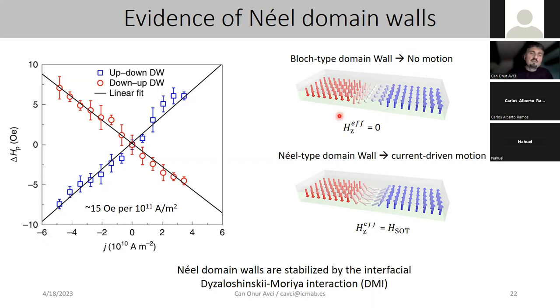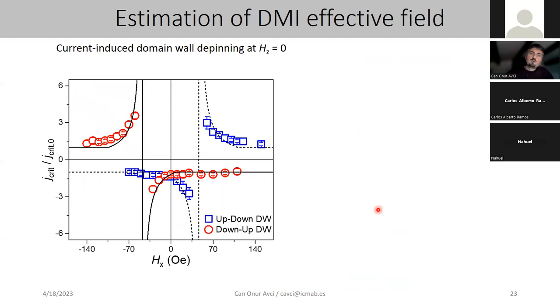We know that the spin-orbit torque or the damping-like torque cannot act on a Bloch type domain wall, which means that the domain wall cannot be Bloch type, it should be Néel type. And then we saw that, to our surprise, these domain walls were actually Néel type. Therefore, we are able to see this domain wall motion. So to quantify this Néel type domain wall,